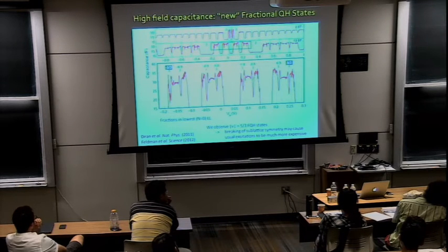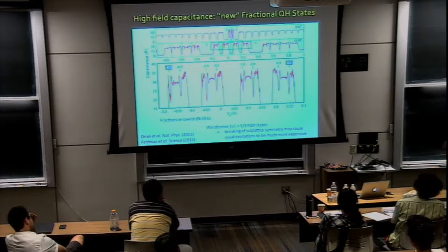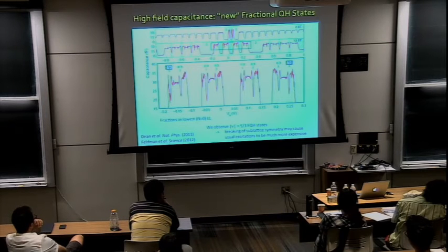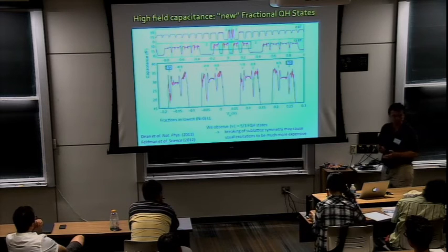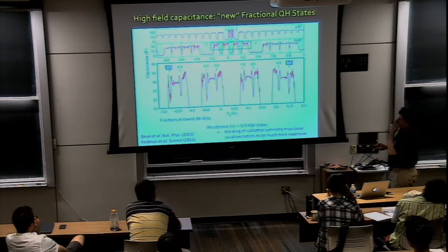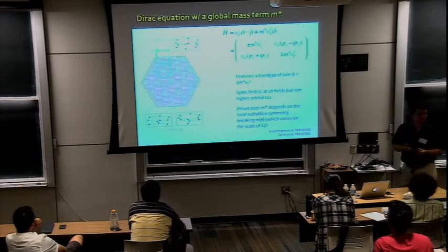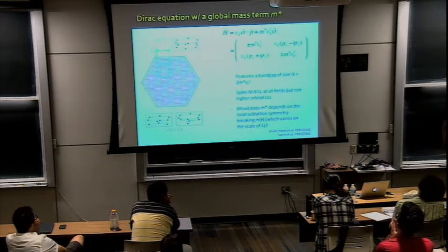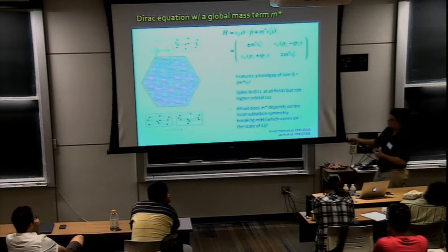graphene. Okay, and people thought that the reason why you don't see a gap is because it's a very small excitation to get to 5/3. Because now we're breaking sublattice symmetry, now we're distinguishing the two sublattices, we're making those excitations a lot more expensive, and that's why you see a very pronounced 5/3, whereas before it was absent. Okay? So we think this is again consistent with the breaking of sublattice symmetry that we see in these devices. But if you think about it, this is kind of strange, isn't it? Because you have a Moiré wavelength of order 10 nanometers.